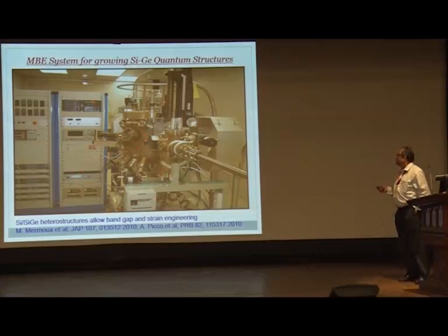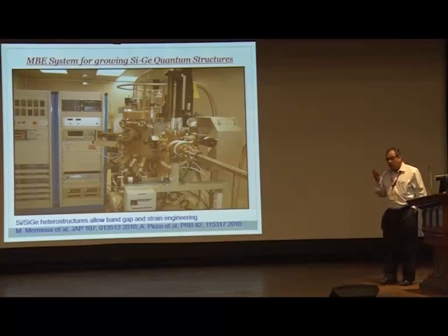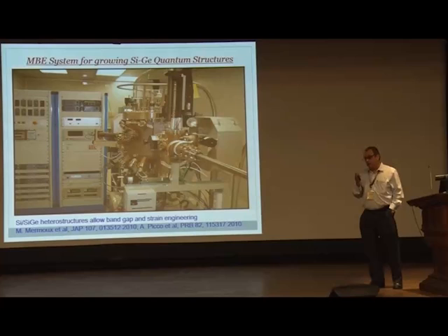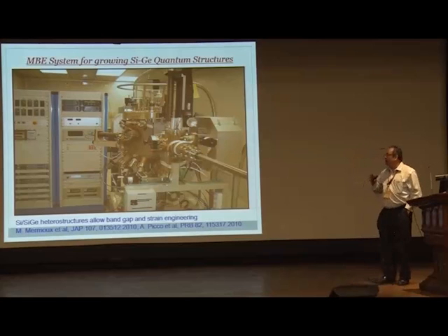growth parameters so well. As you know, everybody wants silicon to be an optical material, but it is not, because it is an indirect band gap, and all this known story. You can in principle make it an optical material by making quantum dots of germanium inside silicon, because the moment it is a quantum dot, these are discrete levels, as I showed you, and discrete levels should not be related to this indirect semiconductor physics.